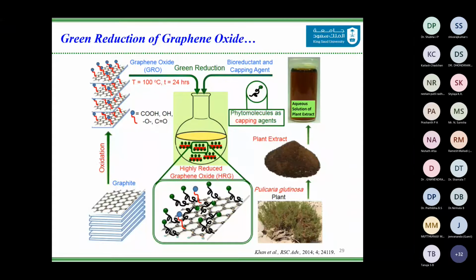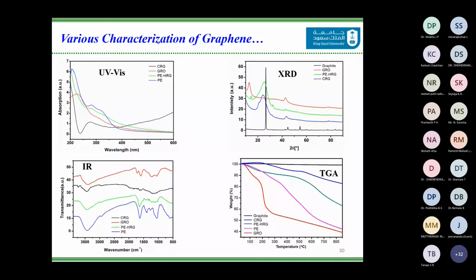So to begin with, we have done the synthesis of graphene oxide, and we evaluated it using UV spectrum. UV spectroscopy is a very sensitive spectroscopy for us to understand what is going on. Graphene oxide usually gives absorption bands at 230 and 301. The red line is graphene oxide. It gives peaks at 230 and 301. However, the desired product that we want is highly reduced graphene, which does not have these two peaks.